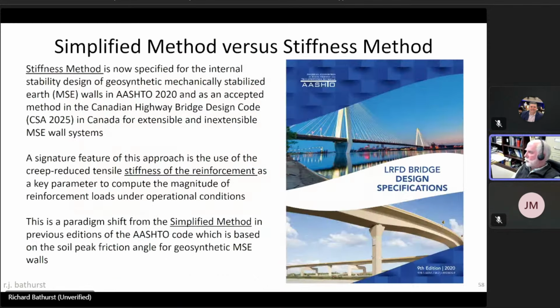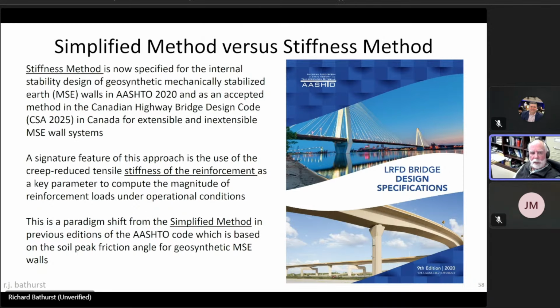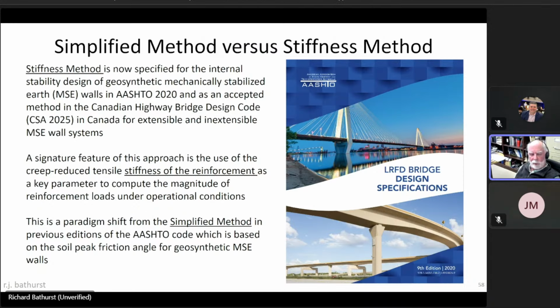In fact, this stiffness method is now specified for internal stability design of geosynthetic mechanically stabilized earth walls in AASHTO 2020. And it's an accepted method in the equivalent Canadian Highway Bridge Design Code, although in the Canadian code we use it for both extensible and inextensible reinforcement. And again, the signature feature of this approach is that it uses the stiffness of the reinforcement as a key parameter to calculate loads under operational conditions. And this is a paradigm shift from the simplified method, which was based on the soil strength, not its stiffness.